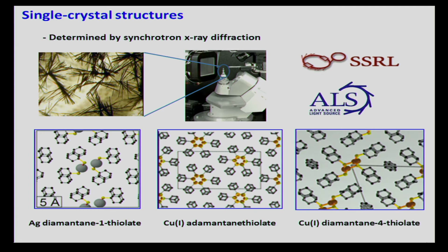And then when you look at the copper adamantane thiolate, what you have is instead a rosette structure where you have 6 diamondoids surrounding them and having a hexagonal sort of copper sulfide in the center. And then when you change that adamantane to diamantane, it totally modifies the structure, and then you have this very different crystal structure.